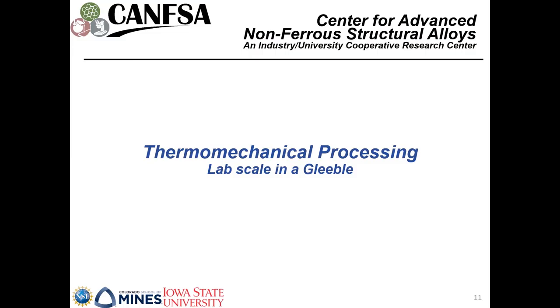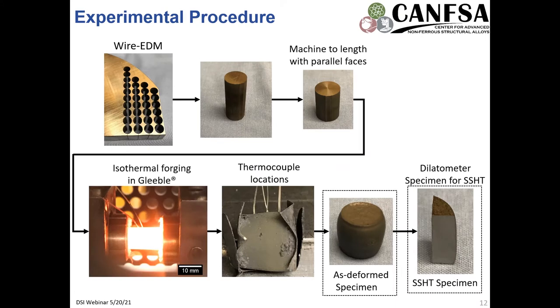And so getting into a bit more detail, utilizing the Gleeble for the thermomechanical processing, we have the experimental procedure schematically shown here. We took a slice of the RR1000 superalloy, and we used a wire EDM to section out samples. Then we machined these to length and parallel faces, attached thermocouples, and did isothermal forging in the Gleeble. And you can see here there are three different thermocouple locations.